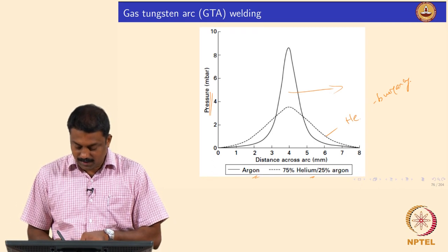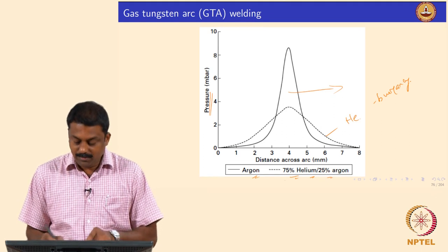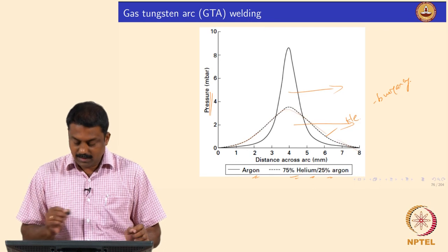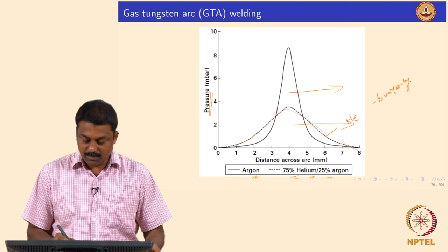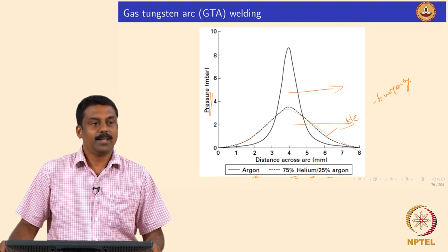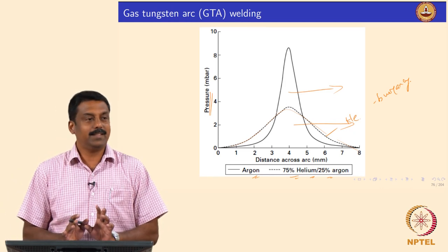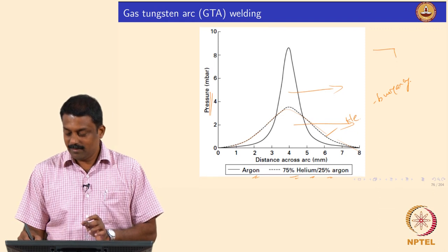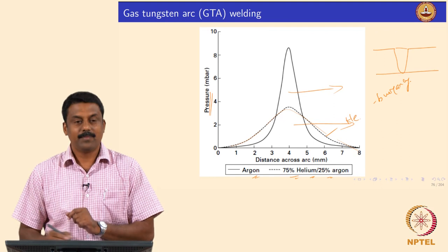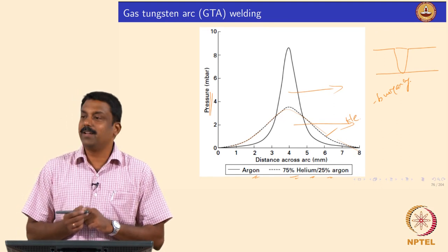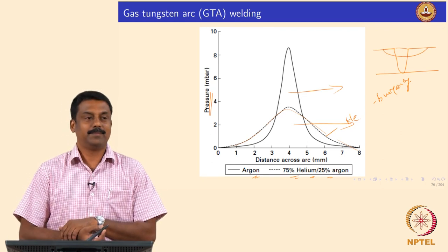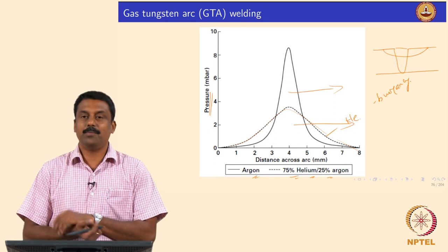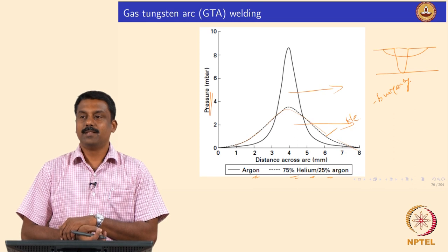Whereas if you mix, say, helium with 25% argon, the helium transfers heat effectively from the centre of the arc to the arc envelope, and during this process the pressure and temperature decrease significantly at the centre because it is spreading out. So now, using the same welding parameters but just changing the shielding gas — argon would give much deeper penetration because heat is concentrated. If you use the helium-argon mixture, your weld bead will be wider and shallower.